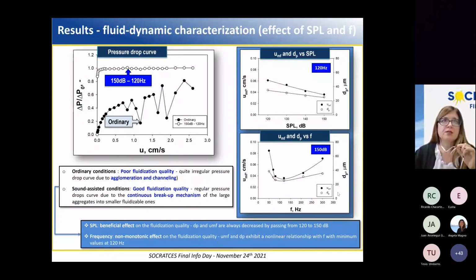In particular, here you can see the dimensionless pressure drop curves obtained at ambient temperature, both under ordinary and sound-assisted conditions. The results show that the fluidization quality is very poor under ordinary conditions. Indeed, the pressure drop curve is very irregular, and the proper fluidization regime cannot be reached due to the occurrence of agglomeration and channeling phenomena. On the contrary, the pressure drop obtained with the assistance of the acoustic field is more regular. This is due to the breakup mechanism of the large aggregates inside the bed into smaller fluidizable ones due to the effect of the acoustic field.